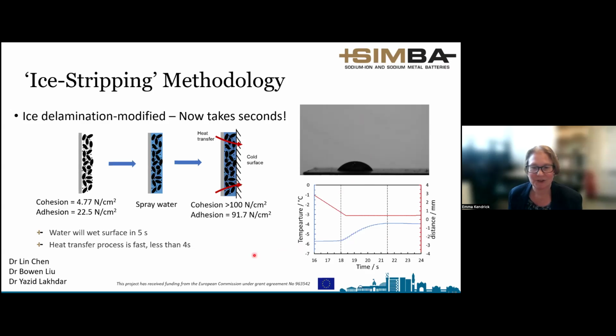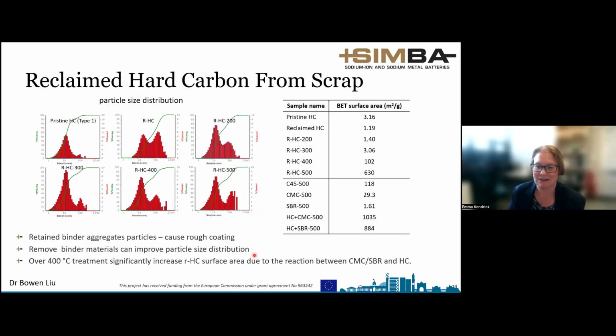So using this, we've tried to look at reclamation and reuse of some sodium-ion samples as well. This is some hard carbon. These are carbon electrodes that we've made with CMC SBR. We've recovered this and then tried to remove the binder by a pyrolysis method. We've heated it from between 200 up to 500 degrees to decompose the binder compounds in there.